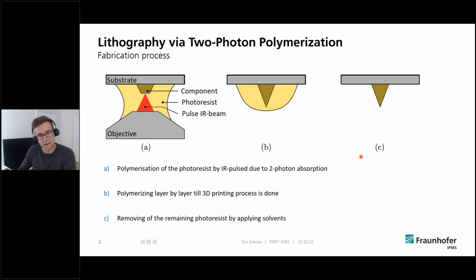Basically, we start out with a substrate that hangs upside down, and on the bottom of the substrate there's a negative photoresist, and this negative photoresist polymerizes when UV radiation illuminates it. In this case, we use an infrared pulsed laser that beams its light into the photoresist. Like I said, we need UV radiation for the polymerization.